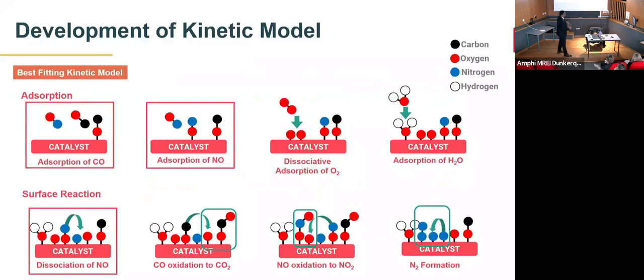So in my catalytic model, the adsorption of CO, the adsorption of NO, and the dissociation of NO were considered as the rate determining steps in my kinetic model. Okay, so that when you are doing the reaction, just one step is limiting the rate, not three. Exactly. But we have 3 different reactions taking place in the system. So we take a rate limiting step for each of these main reactions.